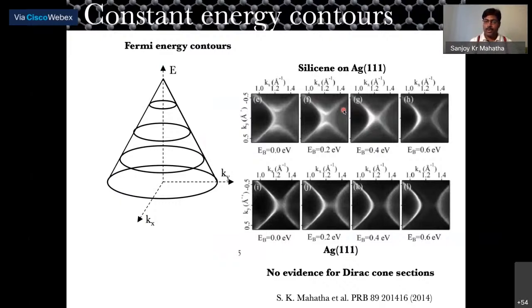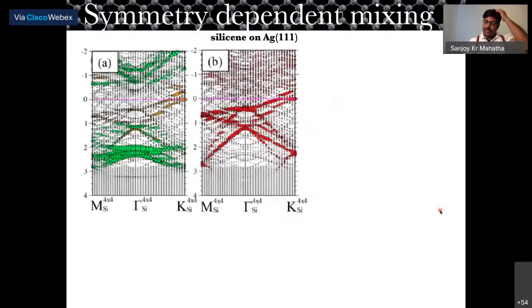Okay, but what we saw here in silver, after putting silicon, is always this kind of dog bone-like structure, not circles. So there is no evidence of Dirac cone sections. And from here we said, okay, there is no experimental evidence of a Dirac cone, but then we must understand what this I band is. And to do that, we did some DFT calculations.